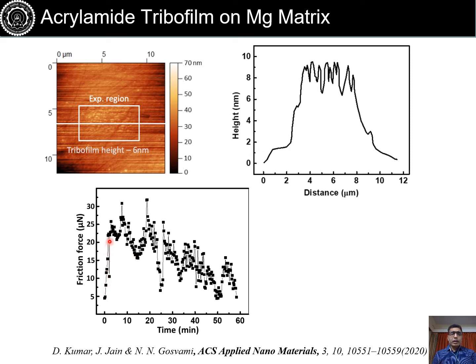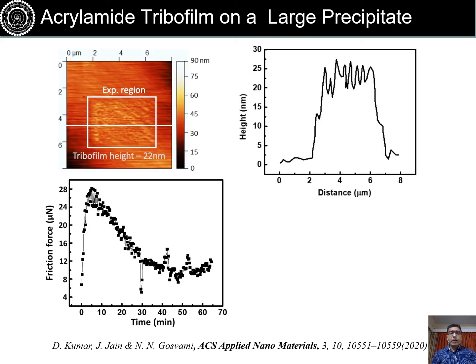The acrylamide based additive also showed very nice friction force variation with sliding time. As the film develops, friction increases quite sharply, but then as the film becomes thicker, the friction continuously drops, which is a good thing, because as the film gets thicker, friction reduces, so overall frictional losses will also reduce with sliding time. On the large precipitate, we saw the film is much thicker, and again we can see that the harder phase is giving rise to a thicker film. So stress is always helping increase the reaction rate. And of course, as the film is thicker, we see a sharper rise in friction and higher friction than the thinner film, and then a sharper decrease in friction as a function of sliding time.